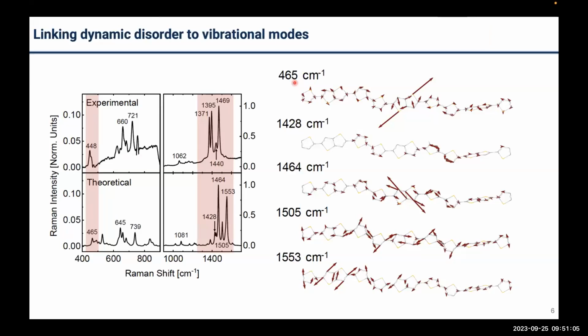Yeah, I would like to comment here. Sure. You don't have to thermally excite a mode if it's dynamic, because quantum mechanically vibration happens at 0 temperature. If you look at dynamic disorder, and we did this as a function of temperature, about 60% you can see at low temperature of the mode.